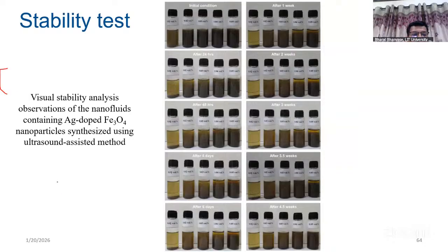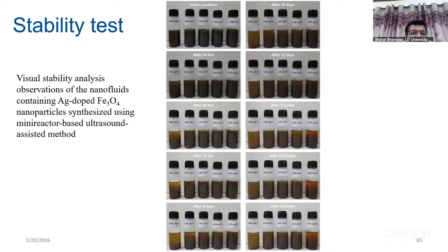For Ag-doped Fe3O4 nanoparticles and nanofluid prepared by ultrasound assisted method, stability is very high. This is the initial condition. If you see after 48 hours, 4 days, 6 days, 1 week, 2 weeks, 3 weeks, some little settling starts around 6 days, and you can see some clear liquid. So settling is there, but after 4.5 weeks it regains good stability. For the Ag-doped nanocomposite prepared in the ultrasound assisted mini reactor, higher stability is observed here, even after 6 weeks the nanofluid remains stable.